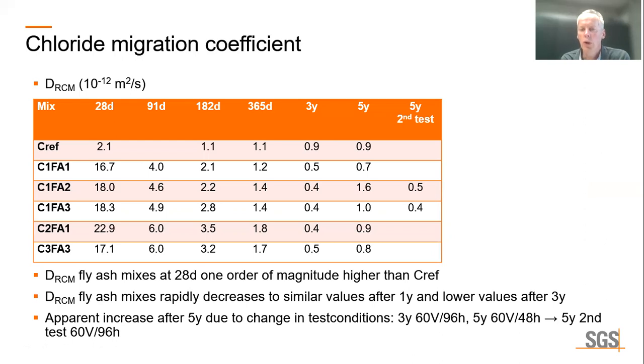We decided to rerun this test after 5 years for 2 of the fly ash mixes at the same test duration as after 3 years, namely 96 hours.